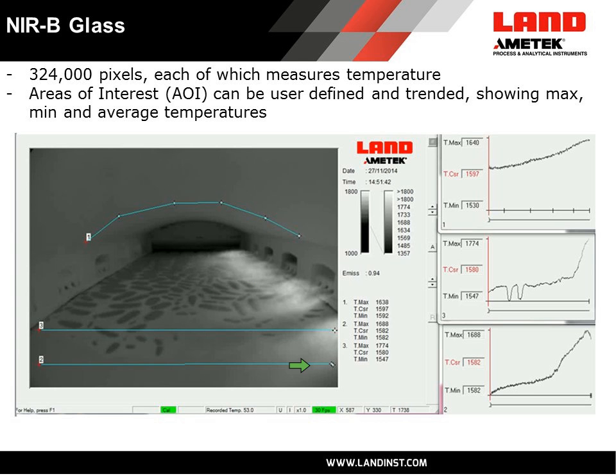And this particular customer has set up profile lines, and these last two profile lines are really to catch the fact that the melt has completed and that batch is now homogeneous within the glass itself. You can also see that they've placed a multi-segment profile across the crown, and this multi-segment profile across the crown shows the temperature profile across the furnace, and this is displayed in here. You can also position anywhere on that profile, and it will show you a line on this temperature profile of where you were looking.